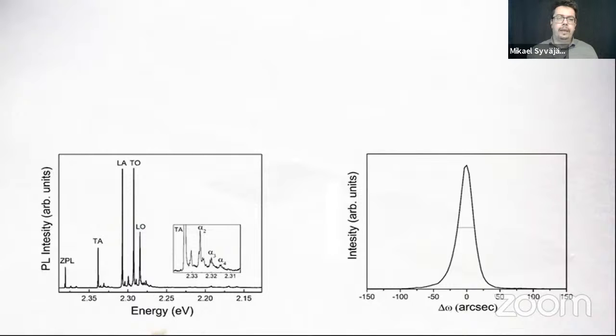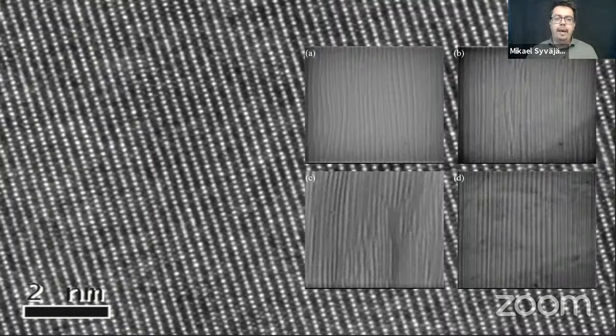And also when we have XRD, X-rays studying the material, when you have the reflection in the material, a broadening of the curve is due to many, many defects which broaden the reflection. So if the reflection is very narrow, then we have a very good signature of the material quality also by the X-ray studies. So this we had in these layers. We also looked into the TEM, so we could see the atomic positioning of silicon and carbon. And on top of this image, you see some surface features. When the layers are growing, they grow step by step, and then you have some irregularities of the steps on the surface. But they are very small. They are not huge and macroscopic. So that was also a good signature that the layers are good.